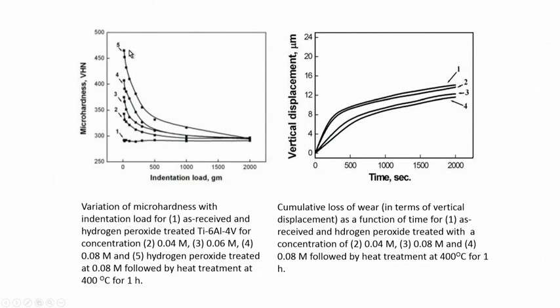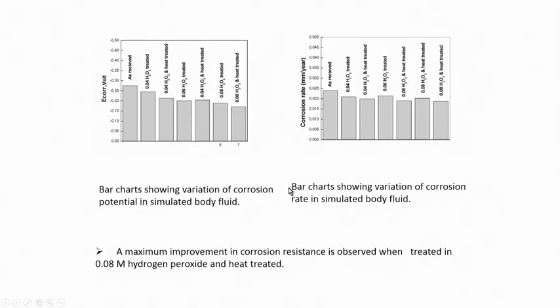And as the hardness varied with the percentage of hydrogen peroxide, we see that there is also an improvement in wear resistance property, which again depended on the hydrogen peroxide concentration. And as we go on increasing the hydrogen peroxide concentration, we find that there is an increase in wear resistance of the coated product, or maybe converted surface.